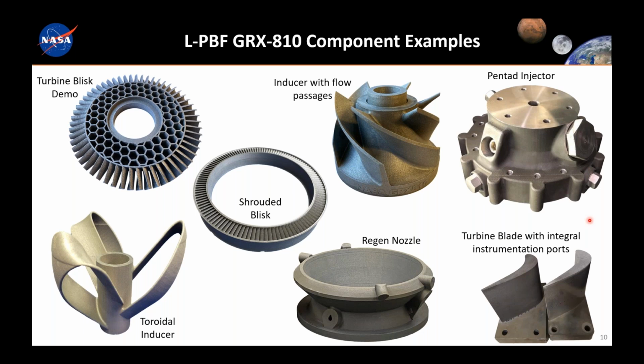So we have built several different components, as I mentioned, both the injectors and the regen nozzles, but also looking at rotating components as well. So blisks for turbines and different types of inducers and blades for some aerospace applications. So we've proven out a lot of the different geometries and thin walls with these components. And again, we see very similar limitations of the powder bed fusion process as you would with any nickel-based superalloy. So I think that again just proves that the material is more or less production ready.